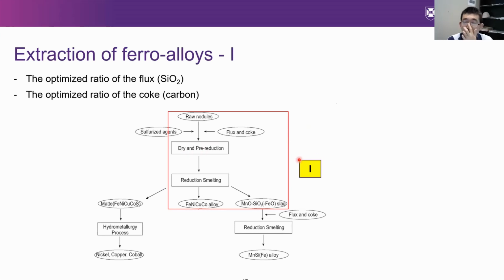And then in the first stage to produce ferroalloys, we add different amounts of silica as flux to optimize the ratio of the flux, and we also add different amounts of carbon as a reductant to produce different compositions of the ferroalloys.